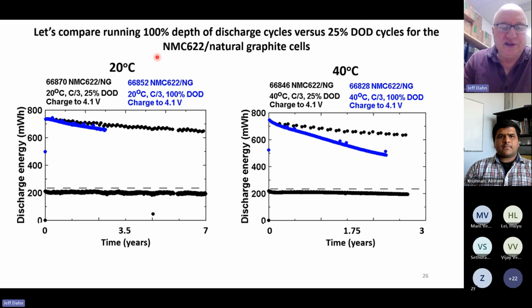So let's just take a look at more data for these cells. We've tested these cells for up to 7 years so far. And the cells where we're doing the 25% DOD shown in black, it's almost no capacity loss at all. And when we look at the 100% checkup cycles, there's very little loss in energy over the 7 years of continuous operation. Whereas when you're going at 100% DOD, you can see more accelerated capacity loss.